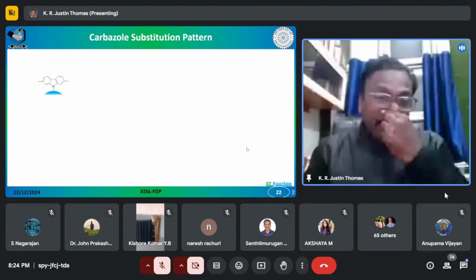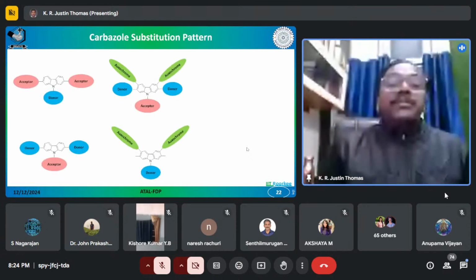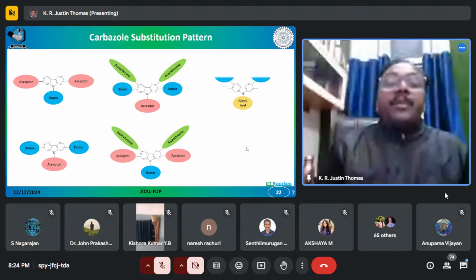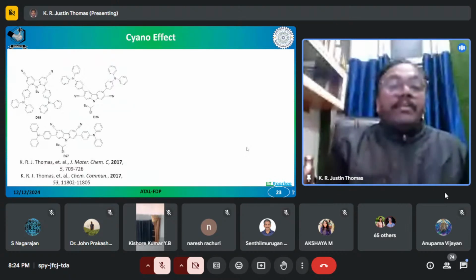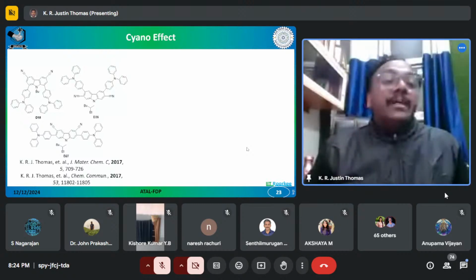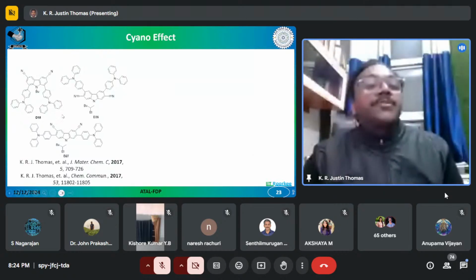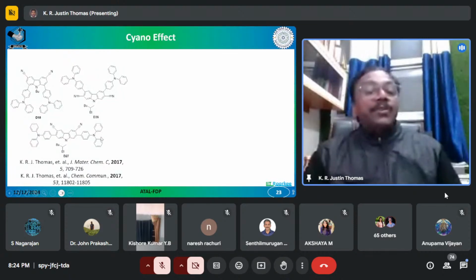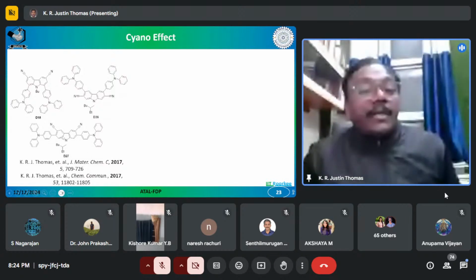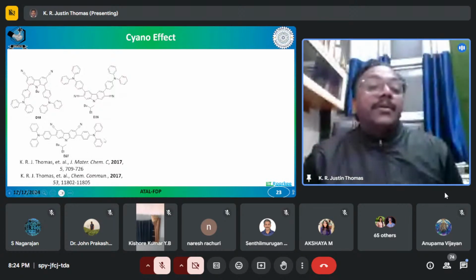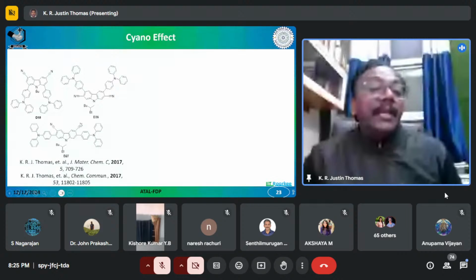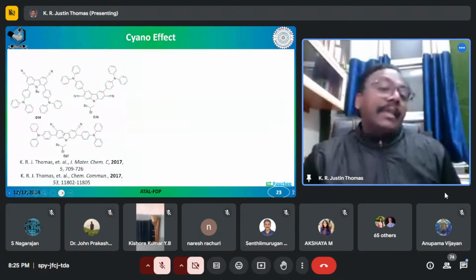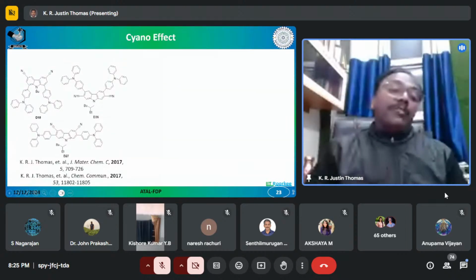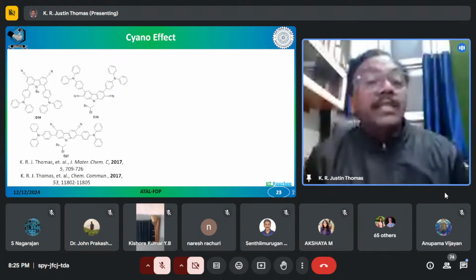Okay, so we have also found that carbazole can also be utilized to design HLCT molecules. We have done a lot of variations by putting several groups on the carbazoles. And I would like to give a very simple effect of cyano substitution. What we found is that when you are having a cyano substitution on carbazole, it leads to a balance between LE and CT states. So suppose, for example, if you are looking at this molecular structure, there is a donor and acceptor in a linear conjugation. So you will have a donor axis here and acceptor axis here. So this acceptor will be interacting with this donor. So there will be a weak charge transfer here and pronounced LE here. So this kind of orientation in this molecule leads to a balance between charge transfer and LE.